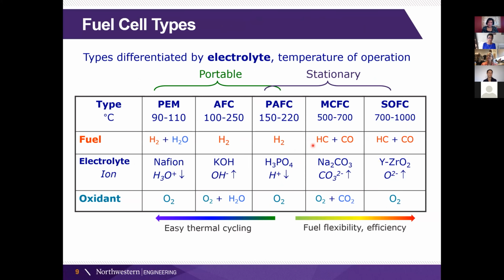Okay, so there are lots of different types of fuel cells, and they're generally differentiated by the nature of the electrolyte. There's the polymer exchange membrane, alkali fuel cell, phosphoric acid fuel cell, molten carbonate fuel cell, and solid oxide fuel cell. You can see that I've ranked them here in terms of the temperature at which they operate. The temperature is really set by the nature of the electrolyte because those ions need that thermal energy to get across the electrolyte. In general, if you go to lower temperature, you have the benefit of easy thermal cycling. And if you go to high temperature, your catalysis is faster, just that thermal excitation over the energy barriers. So you get better efficiency.